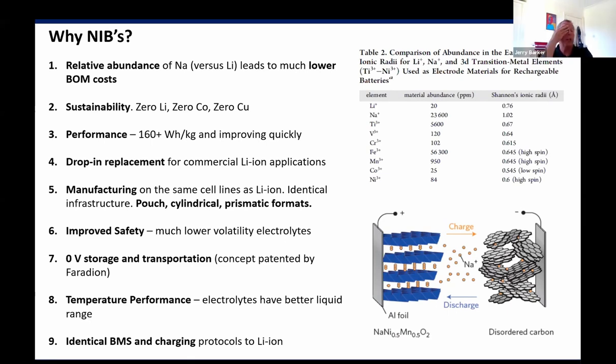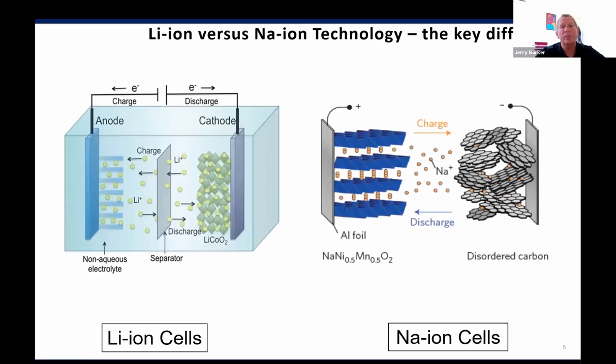And this concept, we identified fairly early on, and we've patented that at Faradion. Our electrolytes, based on the fact that our chemistry is a bit different, are a little bit different to lithium ion and actually have a better liquid range. So we have better low temperature and high temperature performance than corresponding lithium ion. And the BMS and charging protocols are identical to lithium ion, which is also an important advantage.